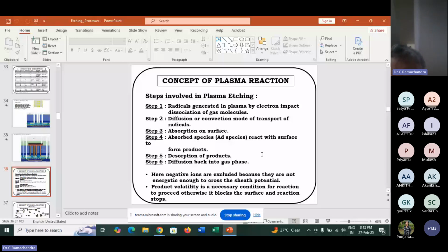So the selection of the proper precursors is very important. That is why it matters how good it is at ionizing and creating the precursors and radicals, and how effectively it moves to the surface of the substrate. That is why the wafer size, the point of injection of the gas, how much distance it has to be kept, and where the vacuum sucking point is, all matter. Gases should not be injected very close to the vent point. Otherwise, you are injecting the chemicals and they go directly to the vacuum pump. They never react with the substrate. It is of no use. Therefore, the point of injection of the gas and the point of vent to the vacuum should be diagonally opposite, or somewhere in between. So there are so many design aspects. I'm just giving an idea.